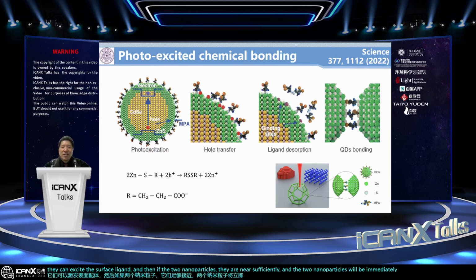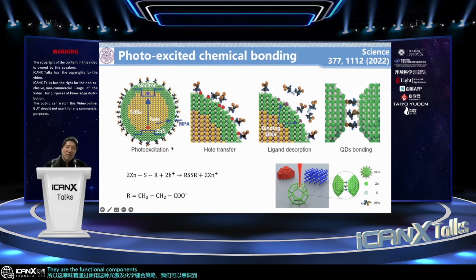In this case, actually, the two nanoparticles are in contact and bonded chemically. It means the nanoparticles are the functional component, but the structure will be produced by the nanoparticles' direct connection, and this connection is a chemical bond. It means they are also the structural component. So by using this photo-excited chemical bonding strategy, we can realize that they are both the functional component and the structural component, both concentrations are 100%. So actually they are the same thing, they are the same particle.